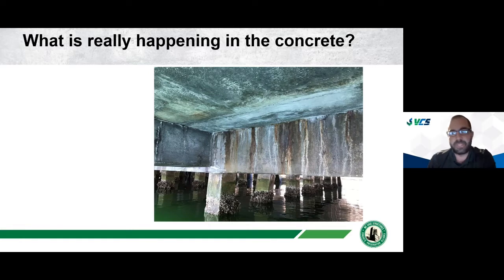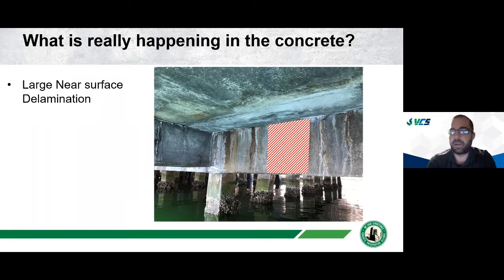So if we go out and do a visual and sounding inspection, we're going to identify maybe, say, a large near surface delamination with the hammer sounding. Obviously we see corrosion staining on this structure here that we're looking at. And so, we may mark out this area that I've hatched out as, okay, that's delaminated. So that's a large near surface delam, and we'd want that repaired. But as we all are probably familiar with, if we sent a contractor in with a chipping hammer to remove that delamination and repair it, it's going to grow beyond the extent that we hatch it out, right? It's not going to stop there. That's the delamination we heard, but there's more damage within that concrete.